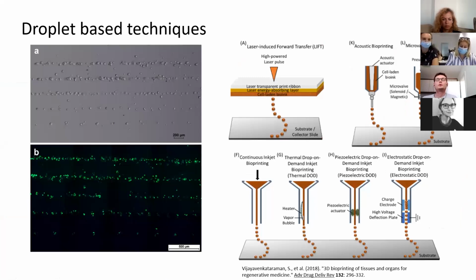The second group of techniques are droplet-based techniques. What you do here is similar to extrusion-based: you have a nozzle and you usually press material through it, but you do it so fast that the surface tension is broken and the material is dispersed into individual drops, which are very small. You can even go into the size of individual cells, which is typically not the case with standard extrusion techniques.